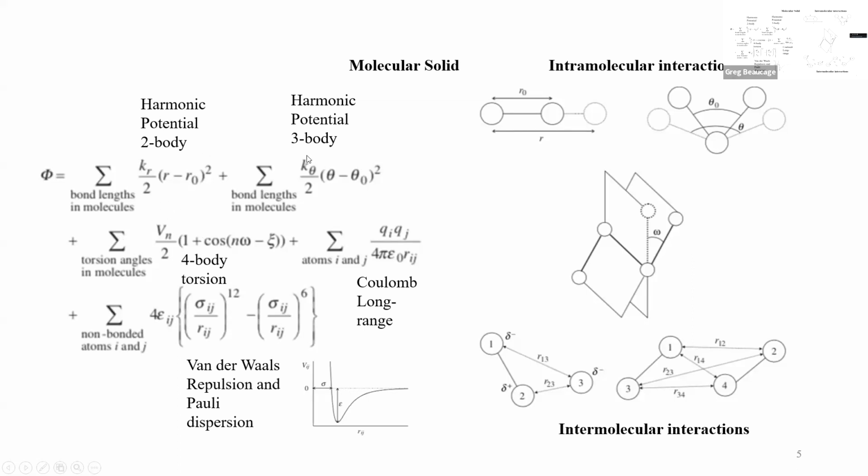It'll ask you for these constants, like what's the spring constant for the bond? Those will be standard input, and they have to be in exactly the LAMMPS format for it to consume them. And then there are Coulombic interactions, so you have a dielectric constant to govern it. You just have 1 over R for the Coulombic, and then the charges multiplied. And then the standard 6-12. The 6 can be calculated. That's the van der Waals long range thing, this kind of sweeping up. And then the 12 is just made up. The 12 is a made up thing. So that's the wall, that's the hard core.